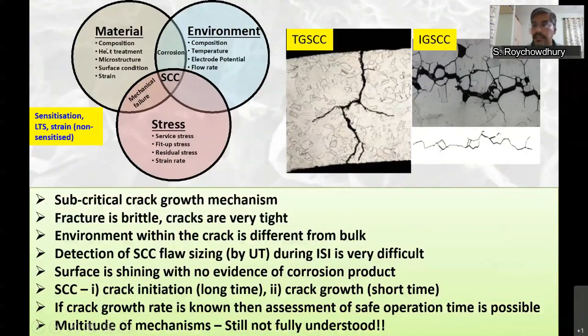You need a conducive material, which will tend to crack. So for stainless steels, what is the material condition? Sensitization, low temperature sensitization, and of late, over the last maybe 15 years, it's been seen that even if austenitic stainless steel is non-sensitized, with no chromium carbide precipitation, yet it undergoes IGSCC in reactor environment, high temperature, high pressure water, if it is strain hardened. If it is strain hardened, it will undergo IGSCC.